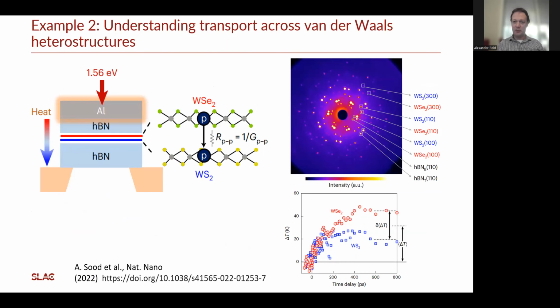Another excellent example coming from the solid state area is exploring thermodynamics across heterostructures. In particular, this work was looking at this across a van der Waals bond, looking at heat transport between two monolayer films with this van der Waals bond in between, and understanding the physics of that process. Via the electron diffraction pattern, which is shown here, we're able to identify the actual peaks of the individual monolayers in this heterostructure. And then via different ways of applying energy and heat through this heterostructure, we're able to measure basically the thermal resistance between these two layers in a device-like structure. And so via this Debye-Waller effect, you can see the temperature difference and how that evolves.